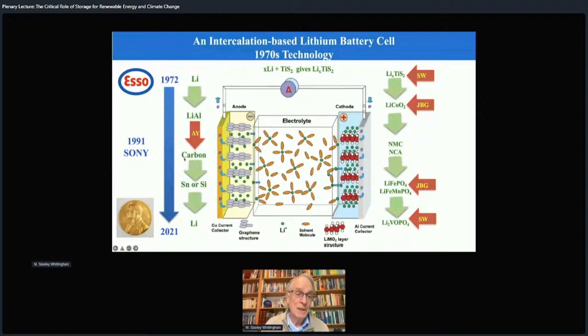But the challenge with this is it takes 72 grams of carbon to store 7 grams of lithium, and the carbon, in fact, takes up half the volume of the cell. So if we want high energy density systems, we've got to get rid of most of the carbon. The present approach here is to look at tin or silicon. Both of these react with more than 4 lithium ions each. So their volumetric energy density is essentially the same as lithium. And the holy grail is to go back to lithium metal itself.